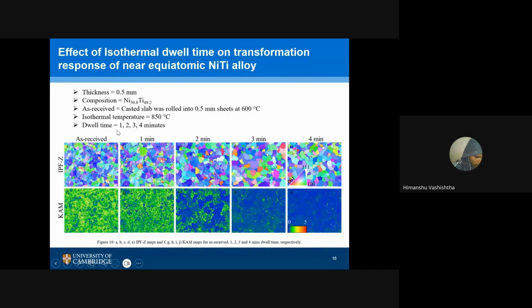So what we did: first we waited for the furnace to reach the temperature of 850. After reaching 850, we are putting the sample in - not from the initial state - so that's just a dwell time of 1 minute. We put it for 1 minute, removed it, 2 minutes, removed it, 3 minutes, and 4 minutes.